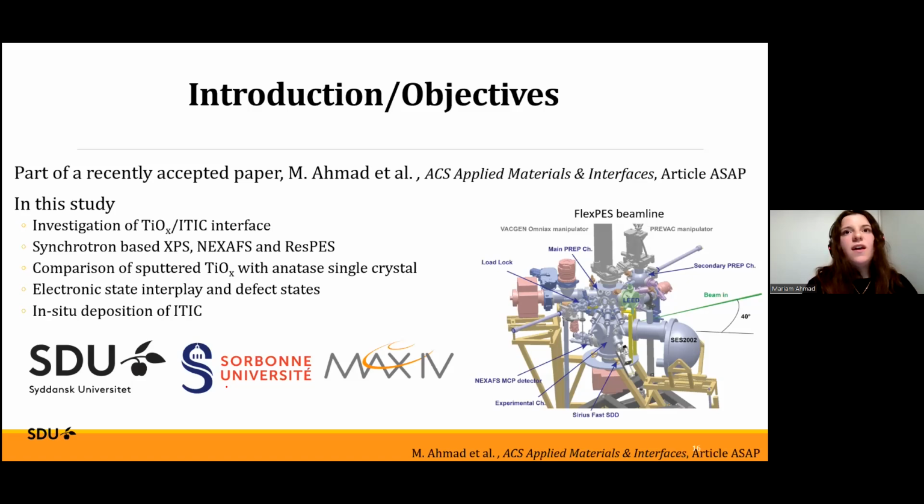Namely, we studied the electronic state interplay at this interface and defect states to try to understand why we don't see this photocatalytic degradation of ITIC on the sputtered titanium oxide, and why this titanium oxide has a reduced photocatalytic activity. So we went to Max IV to this beamline that's called FlexPES, which is a beamline where you can do XPS and X-ray absorption spectroscopy. And we did XPS, NEXAFS, and RESPES measurements on the sputtered titanium oxide before and after deposition of ITIC.